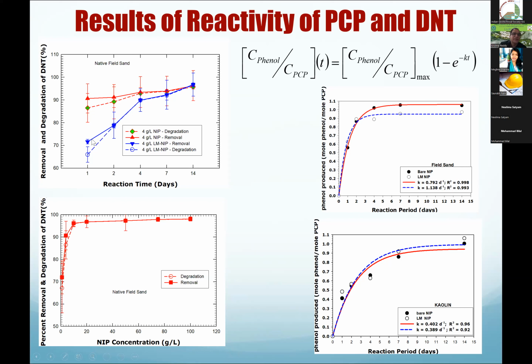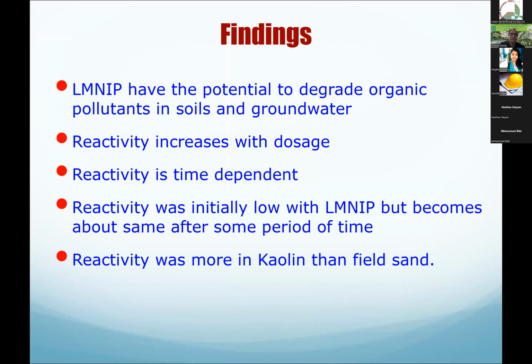So what I'm trying to say is, this lag time for the removal of lactate coating really helps us, or gives us the chance for the nanoparticles to be transported into the sand to the distance that we want, and then the reactivity goes up. So the conclusion is, if you modify the bare, highly reactive nano iron particles with lactate, it's going to reduce the reactivity, but the reactivity will be recovered as the coating gets removed. And that's the conclusion that we got out of this one. Very interesting results with the PCP, also similar things.